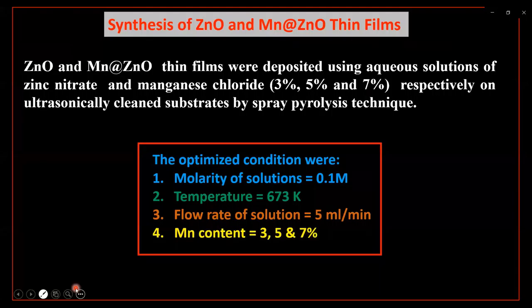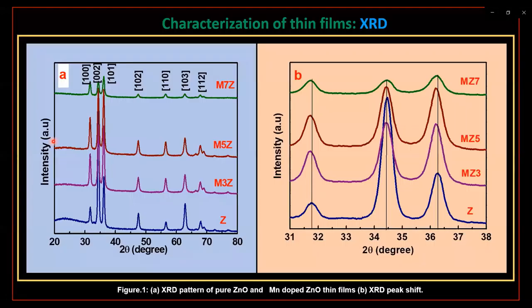The synthesis of ZnO and Mn-doped ZnO thin films. ZnO and Mn-doped ZnO thin films were deposited using aqueous solutions of zinc nitrate and manganese chloride with the help of the spray pyrolysis technique. For this deposition, the optimized conditions were: molarity of solutions 0.1 molar, temperature 673 Kelvin, flow rate of solution 5 ml per minute, and Mn content of 3%, 5%, 7% doped in the ZnO thin films.